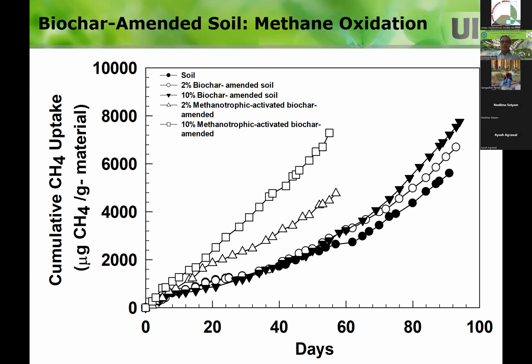So if this happens initially for a few days, you may not have, for example, 60 days, you don't have anything happening. But after that, this one with the biochar, they are taking off with high methane oxidation. And of course, we did only up to 90 days or so. But if you don't want to have this lag time, you can actually activate the biochar with methanotrophs. So you can create a methanotroph culture, and then you basically spray it on biochar, and then use that one in the soil. So if you do that one, you already have methanotrophs in the biochar system, and you see that there's no lag time.